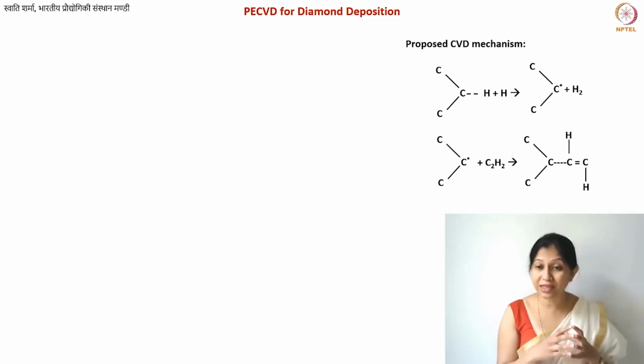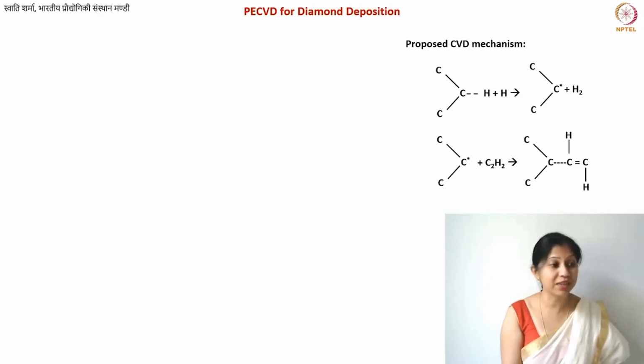Acetylene species can be present even if you did not use acetylene directly as your carbon source. You can even use methane or benzene or anything else, and still you will have some acetylene species present. This species then gets attached to your carbon atom, and there you now have 4 carbons. Now you have the sp3 type structure completed.